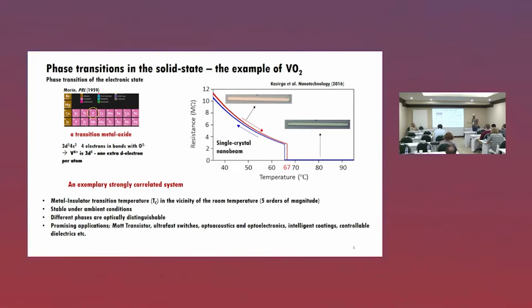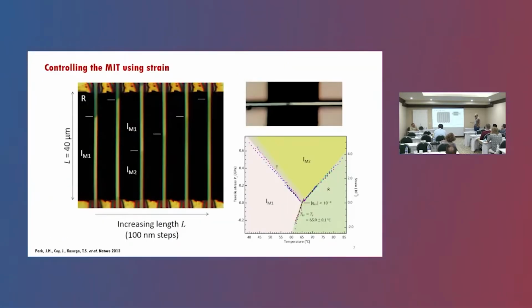This is an interesting transition because the resistivity changes on the order of 5-6 orders of magnitude, and it is coupled to an optical phase transition as well. So, in our past efforts, we tried to understand this phase transition, and we applied strain using a MEMS device. If you could play the video, by changing this gap size, you can see that this phase boundary can be controlled, and this allowed us to extract a phase stability diagram of this material and a triple point in a solid state system for the first time.